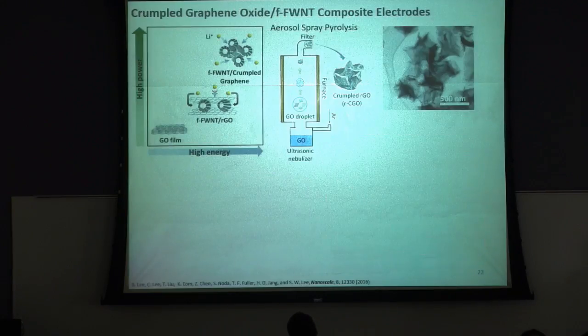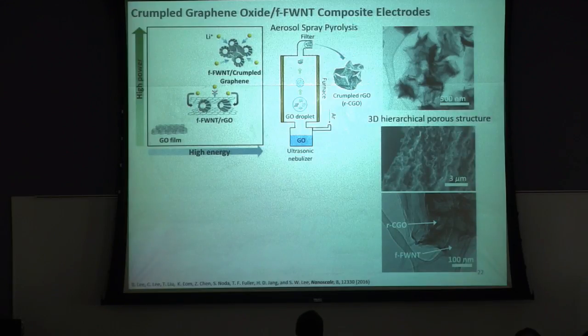So then, to further improve this performance, we decided to use 3D graphene. We can synthesize this kind of 3D ball-shaped crumpled graphene oxide using the aerosol spray pyrolysis method. So this is the shape of the 3D graphene. Then again, we mix this 3D graphene with the functionalized carbon nanotubes. After the vacuum filtration process, we can get this kind of 3D hierarchically porous structure. Now the graphene oxides are anchored within the carbon nanotube networks.